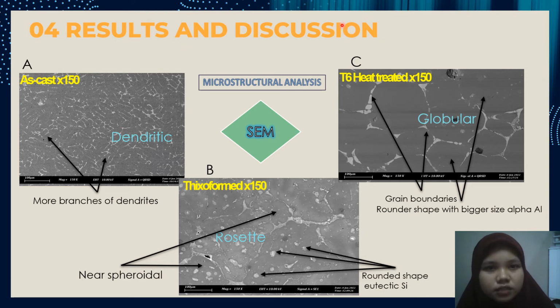And the near spheroidal alpha aluminium phase appearing in figure B in the THIXOFORMED process shows that this process is better than the conventional forming process. Okay, for figure C, short T6 heat treatment affected the eutectic silicon morphology, and the eutectic silicon particles spheroidized, acquiring a more rounded shape and increasing significantly in their size.